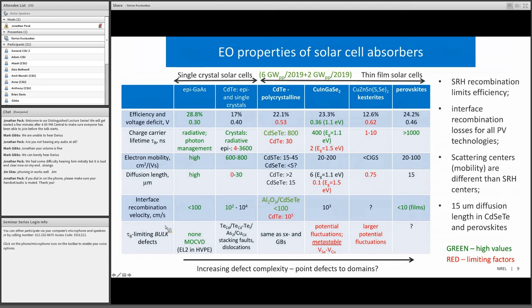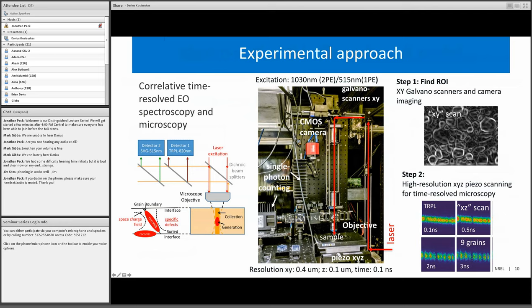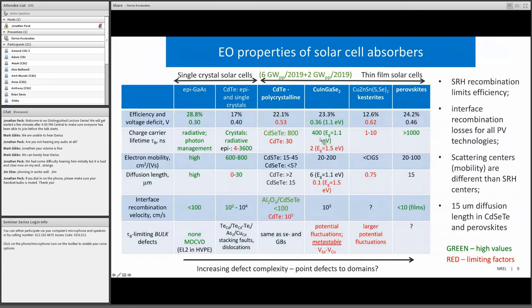The carrier lifetimes in cadmium telluride approach 1 microsecond now, and that's a big advantage of cadmium selenide telluride versus cadmium telluride. The carrier lifetimes are also very good in CIGS, especially the lower band gap CIGS, and they are extremely high in perovskites. They exceed microseconds. Now, the mobilities are actually high in single crystals, but they're very similar in all thin film technologies. So that means that even if the carrier lifetime is lower, the mobility is still high, which strongly suggests that the defects that limit mobility are different than defects that limit carrier lifetimes.